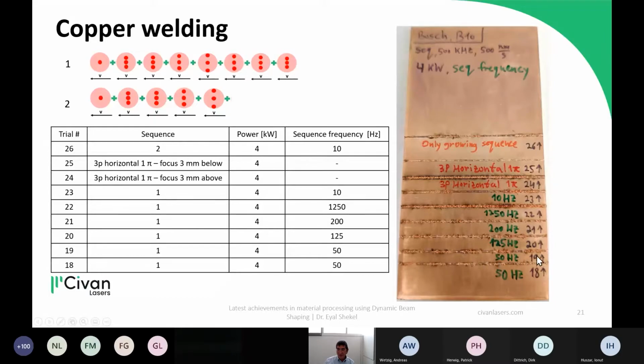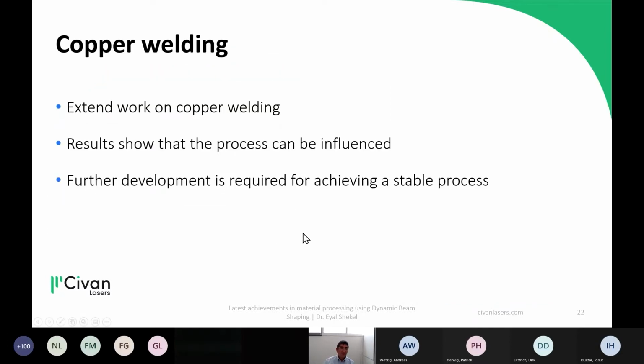And really, again, by changing the frequency of the sequence, you can see different behavior in the copper. The idea was to see how it behaves and try to get a very good, fast and deep penetration weld in the copper. So this is still work that's being done. It's clear that the different beam parameters affect the process and the quality of the weld. We still have to do further work to develop the best results for the copper.